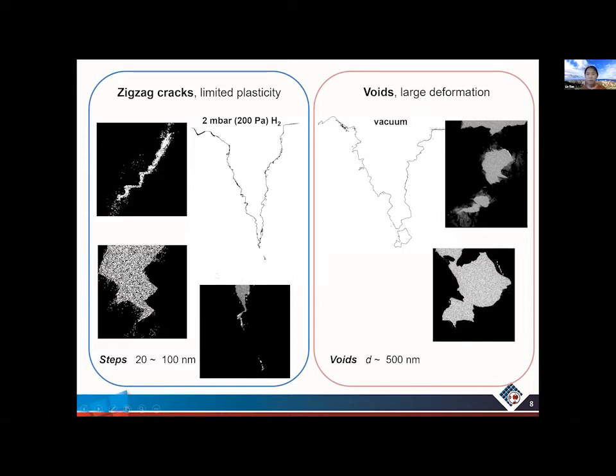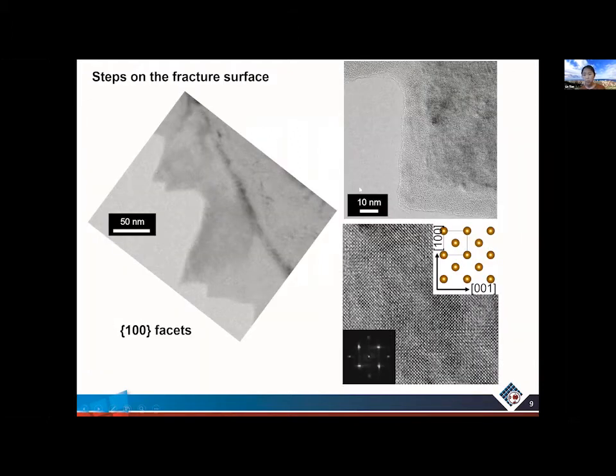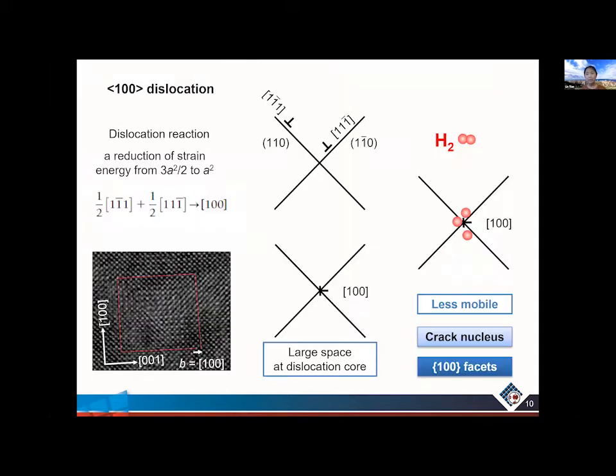So back to the steps. We measure the steps. The size is around several tens of nanometers to 100 nanometers. If we look closer at the steps, we can also take high resolution images of the steps here. It shows most of the steps are {100} facets, which also explains why the steps have a right angle staircase shape. So here I would like to propose a mechanism for how these {100} facets come about.